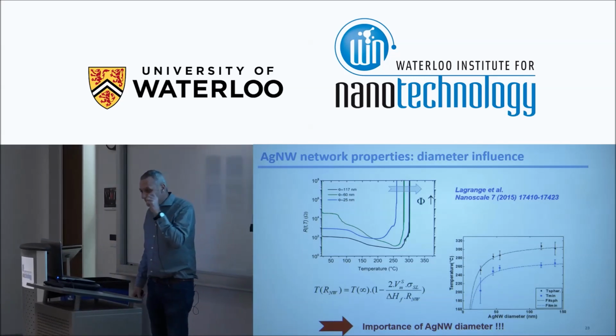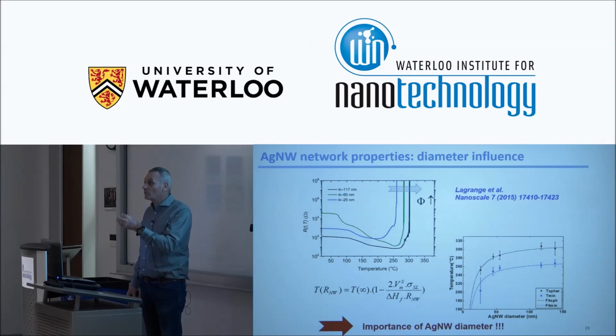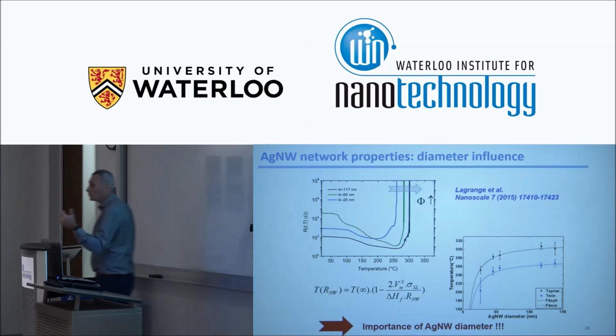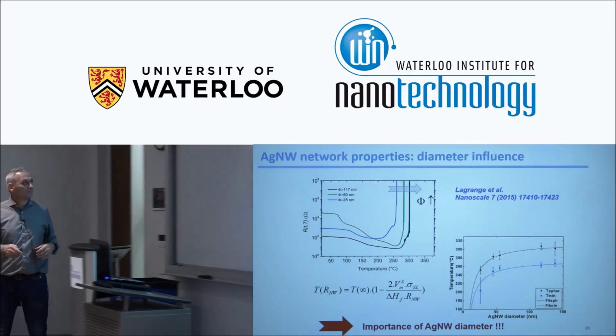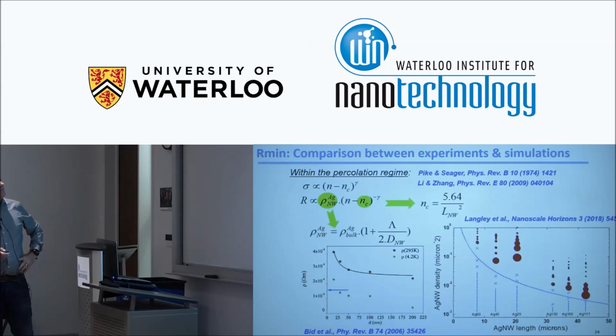So when the nanowires have a smaller diameter, we have more and more problems with stability. It's nicer for the aspect factor, but we are also going to become unstable more and more quickly. That means at lower temperature and at a lower current density as well.